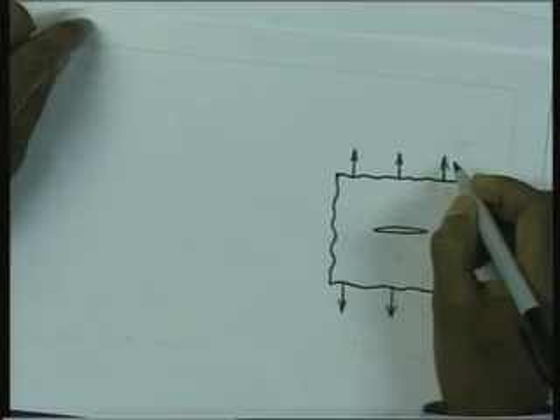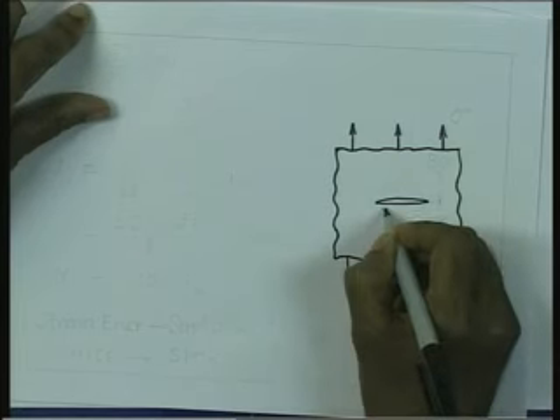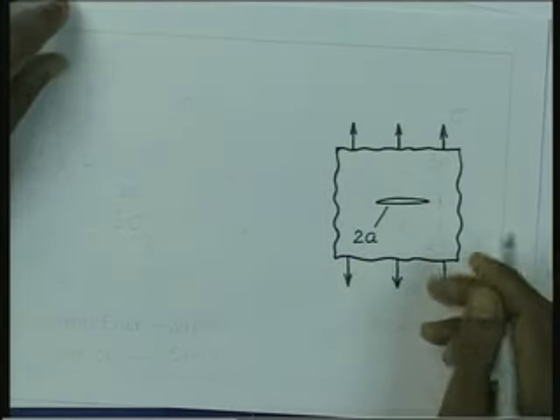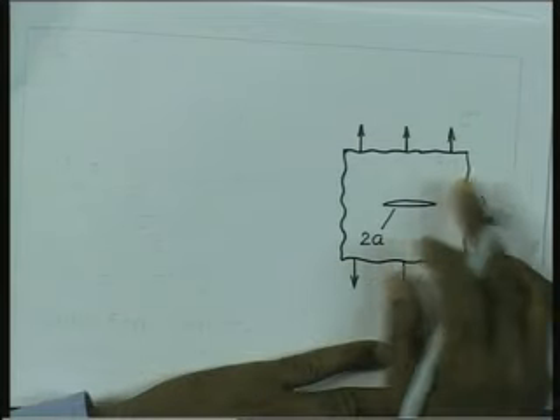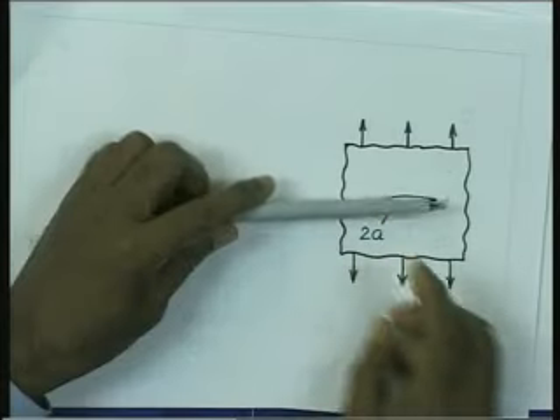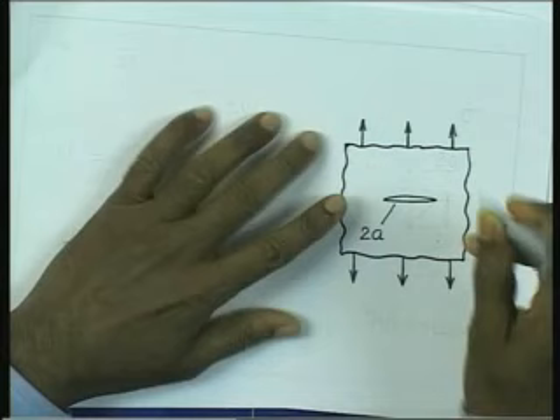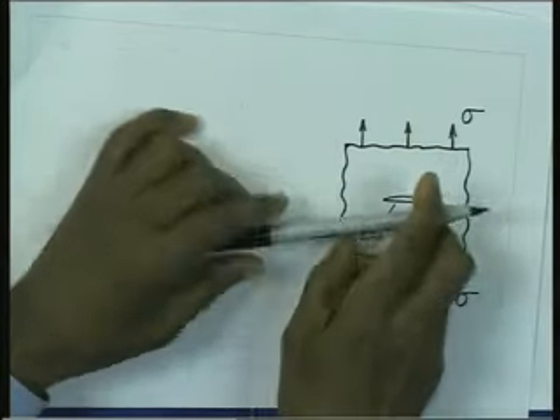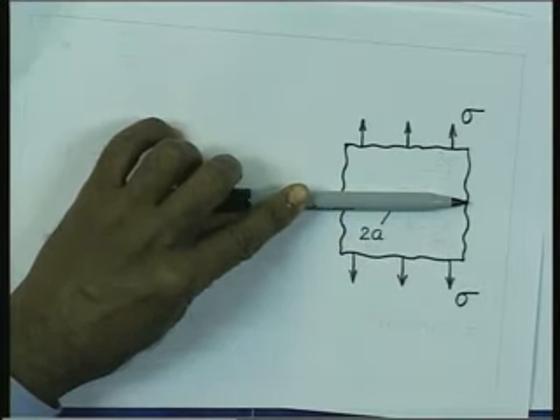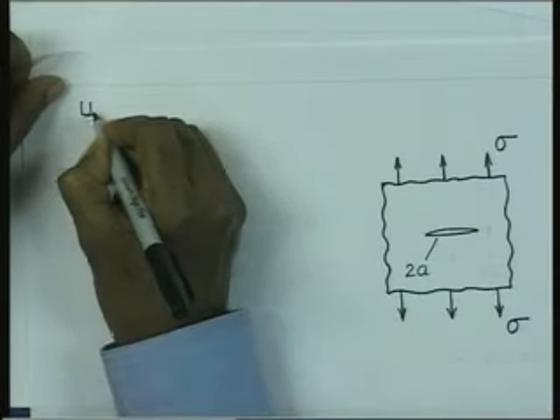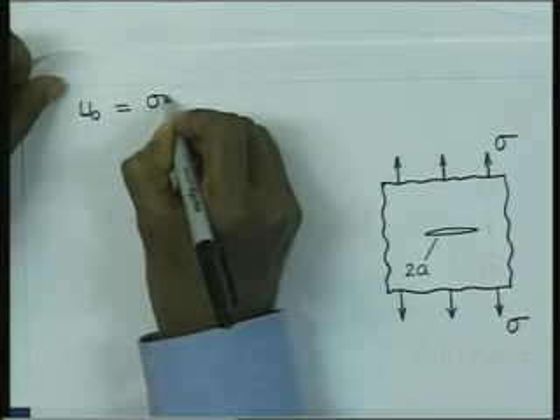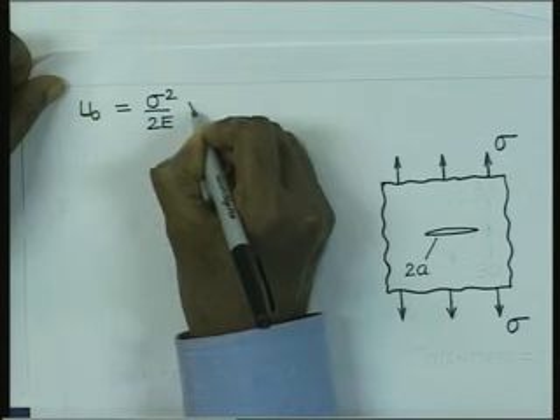So, let us consider the second example, that we have the plate with this loading and the crack is of dimension 2a. If you consider for the moment that this particular component does not have any crack in it, and it is loaded with stress equal to sigma, then the strain energy density at any point is going to be sigma square by 2E, and therefore the total strain energy stored in the body would be equal to sigma square by 2E multiplied by the volume of the body. So, for the uncracked component, the strain energy stored is nothing but sigma square by 2E into the volume of the component.